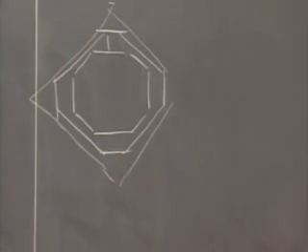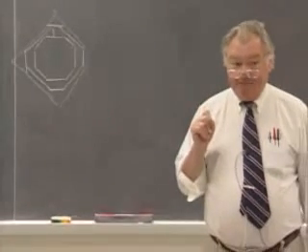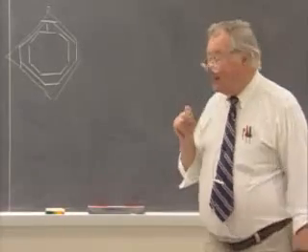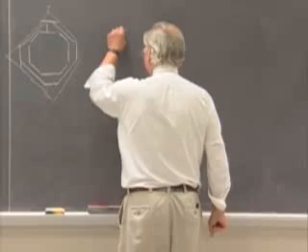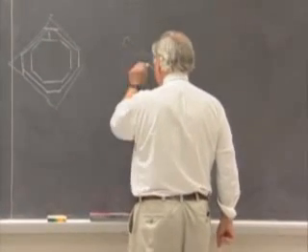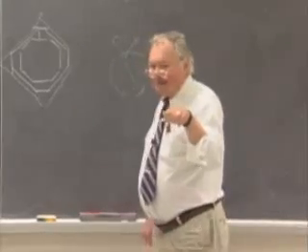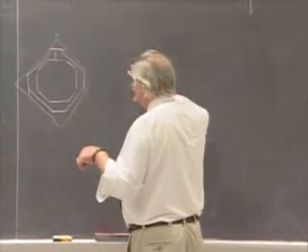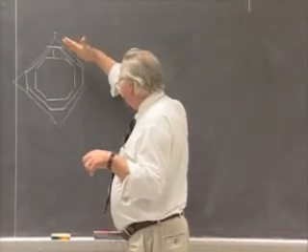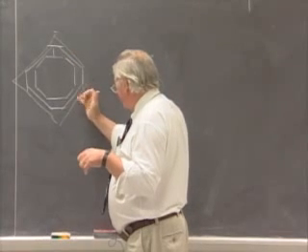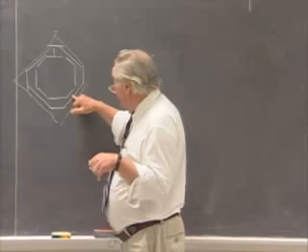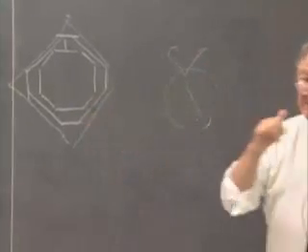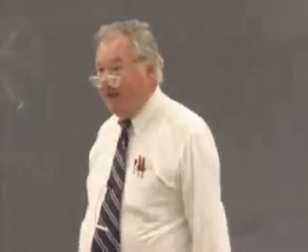This is of great use to the people who want to control crystal shape. And this is very often in very everyday, ordinary contexts. The people who grow table salt, for example, want to grow a crystal that has nice pointy edges, so when it comes down on your tomato, it doesn't bounce off, it sticks to it. So the shape of table salt makes a difference in how it behaves. And the way you change the shape is to find something that will be absorbed preferentially on one set of faces that you would like to have be the faces that appear on the crystal, and that will do the job for you. I'll close with just one final example of this in real everyday industry and technology.